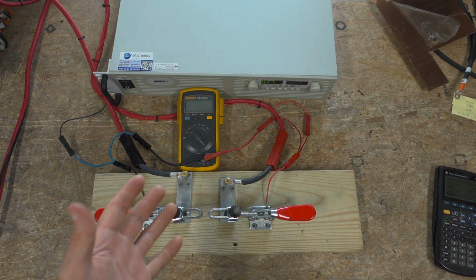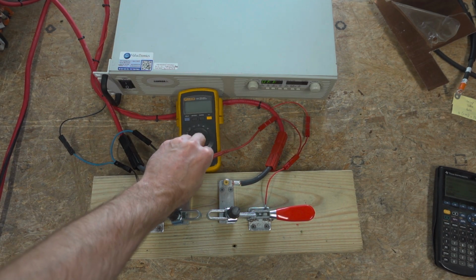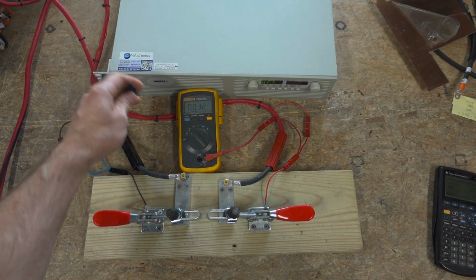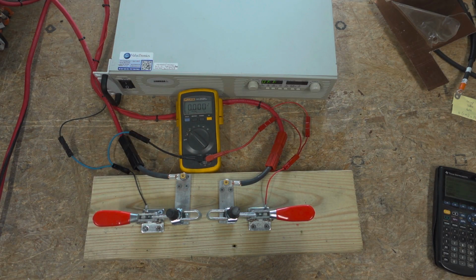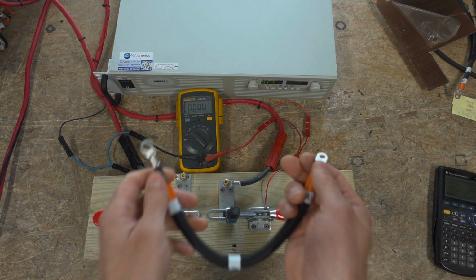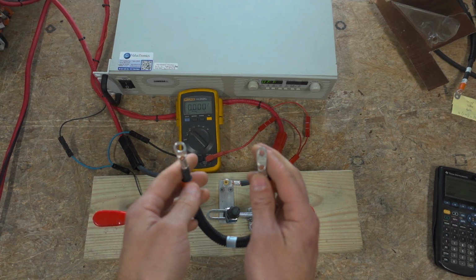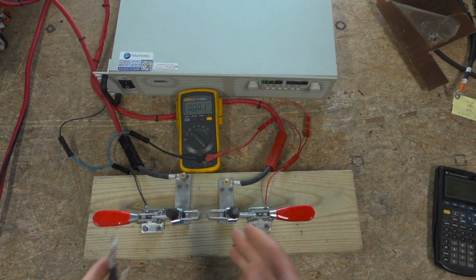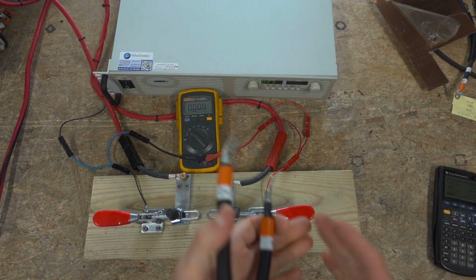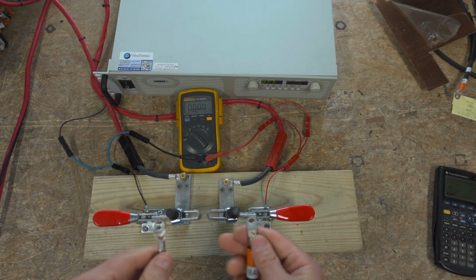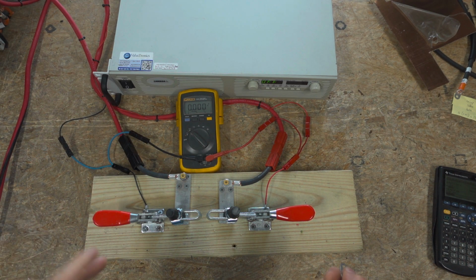So I wanted to show you today my tester that I use on all the cables that I build. The tester shown in the video that I watched has much lower current. I'm not saying it's an invalid test, but when you're looking at something that's at 150 amps in use, and you're testing it with 50 to 100 milliamps, you're not really in the actual range there, and so you get some measurement error.